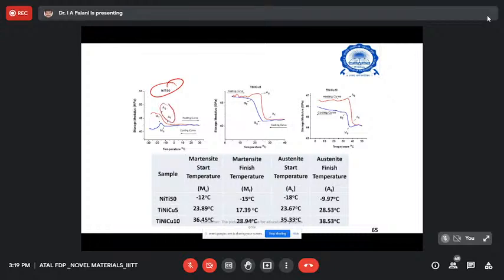So basically, this is with nickel titanium 50/50, where we could easily identify our austenite phase and a martensite phase, whereas the loop was not closing. Whereas in the case of NiTiCu5 and NiTiCu10, we could see a proper loop coming out of it. So basically, this helps us narrow down what is our martensite phase and what is our austenite phase, and how these systems can be used for direct functional applications.